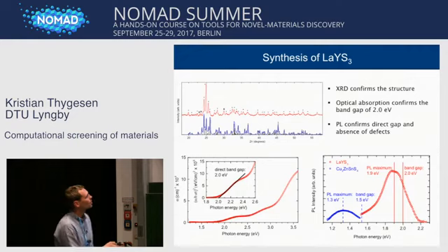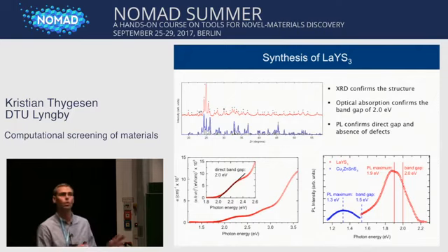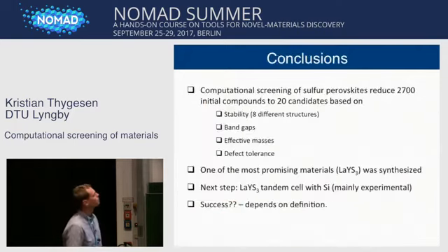And they also confirmed from the very strong photoluminescence peak here at close to 2 eV that this was a direct band gap material as predicted, and that defects were playing a minor role. Because if you have too many defects here and you have states inside the band gap, then the photoluminescence peak will be dramatically lowered. So the intensity of this photoluminescence peak strongly suggests that it's close to being a pristine semiconductor. There might be defects, but they don't introduce localized states in the gap.